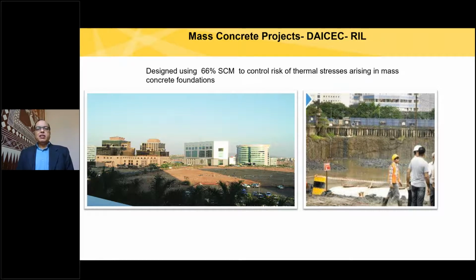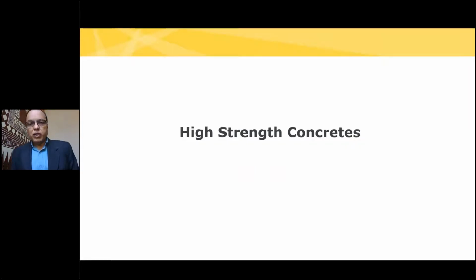That is GGBS. The GGBS that was used was 66%. Why was 66% of slag used? It was mainly to control the thermal stresses that come, particularly in mass concrete foundations. Please note, 66% supplementary cementitious material is used. Therefore, the cement content was only the remaining 34%. Did we compromise on strength? No way. The strength requirement was M50 to M70. Was there a compromise on the slump? No way. Slump was 500 millimeters flowing slump. Therefore, this was a requirement, and that is how it was satisfied.